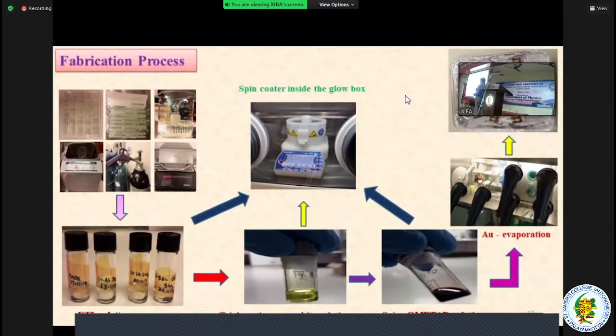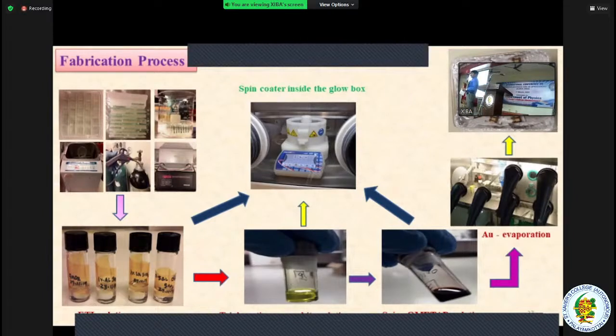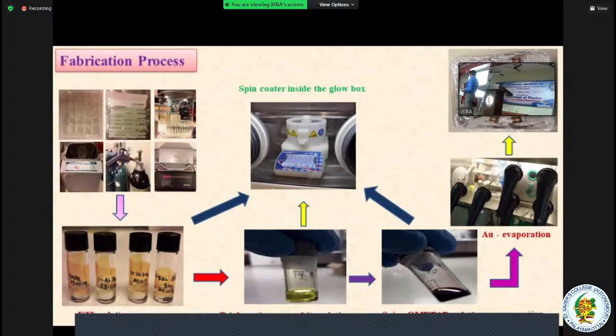This is most important because the thickness of each and every layer is most important. Actually, the ETL we optimized at 100 nanometer, and then the perovskite layer was 430 nanometer, and then the HTL was 220 nanometer, and then the gold contact was 80 nanometer. These are the optimized values of the thickness of the different layers. Next.